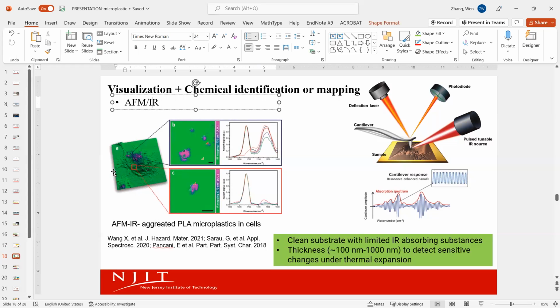So when you map the samples using AFM, lots of people understand that AFM is basically a scanning probe microscope. You're using a very tiny AFM probe to scan over the sample surface. Then you generate morphological images, right? As you can see, their morphology. But again, in our research, we're not just interested in the morphology. We also wonder what they are, right? So this is a problem for most AFM researchers.